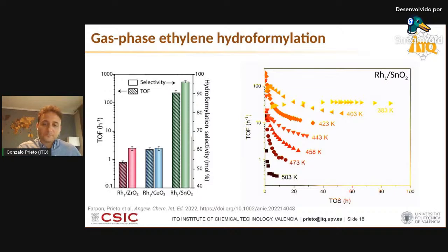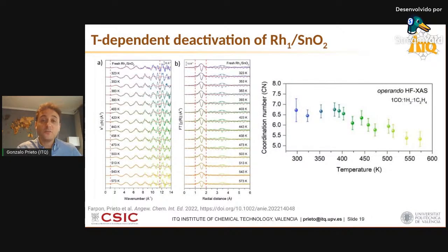So, very nice system. Very active, selective, quite sensitive to the operation temperature. So we initially thought, is this related to metal sintering, or is rhodium agglomerating at these higher temperatures and that is what is killing the active centers? And the answer was no.